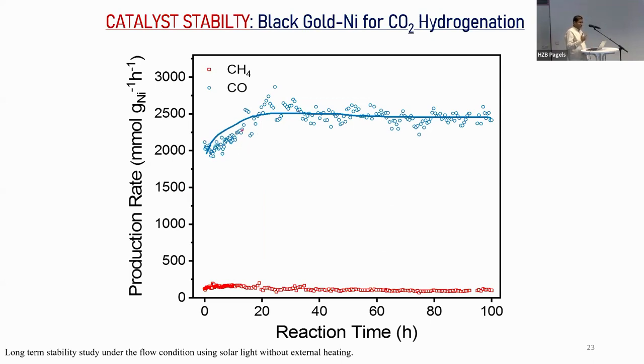This is because nickel is getting reduced. Because you're doing the CO2 hydrogenation, you have hydrogen and you have CO, both reducing agents that can convert some of those unreduced nickel into pure nickel zero, and then you see it's stable for 100 hours. The 100 hours is like the minimum it is stable.